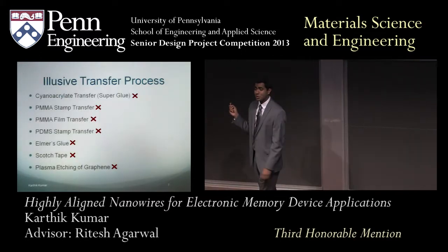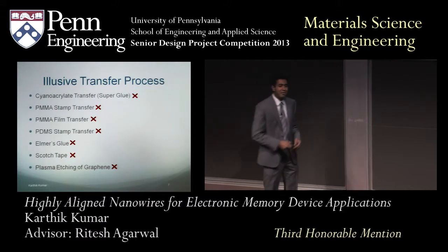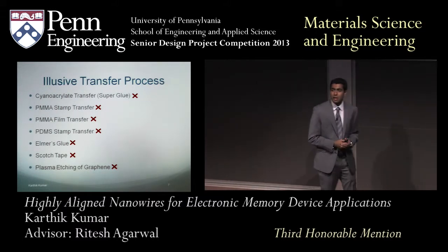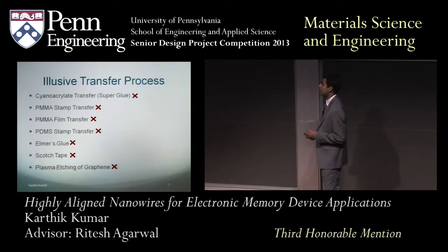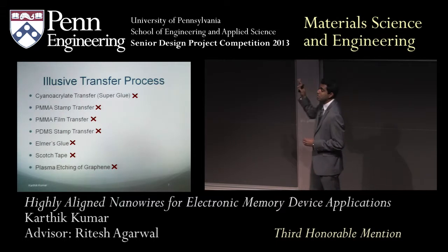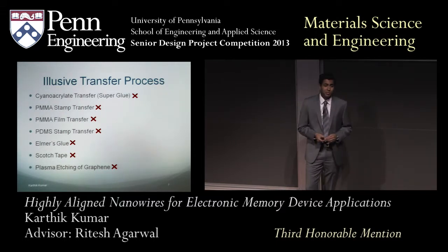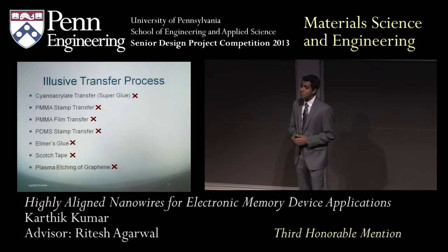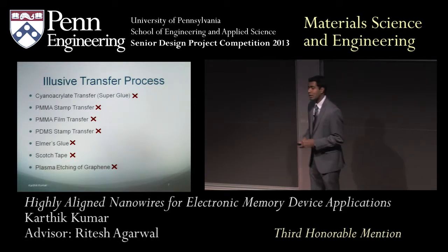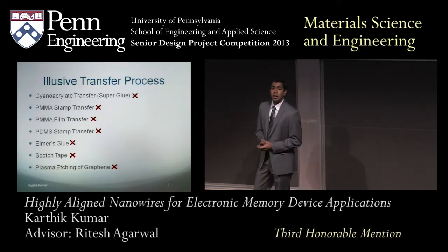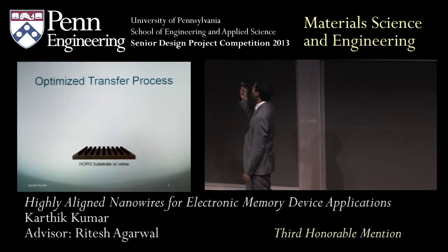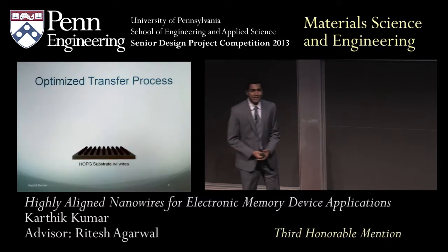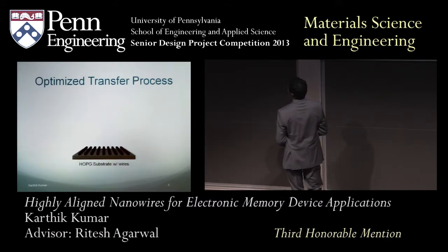Unfortunately, that's where past work was of little help. In fact, this was a turning back point for a lot of groups working on electrochemical step-edge decoration because they just weren't able to get the wires off the substrate. So I tried all of these methods, which were documented in literature, and unsurprisingly, they all failed. So I had to come up with my own optimized technique, and I'll run that by you here.